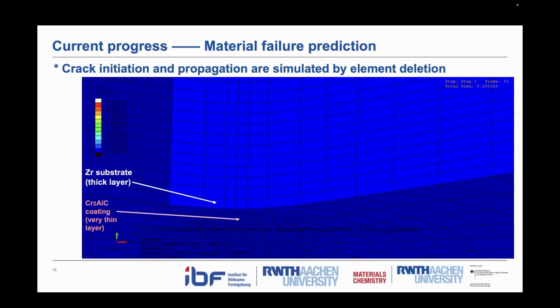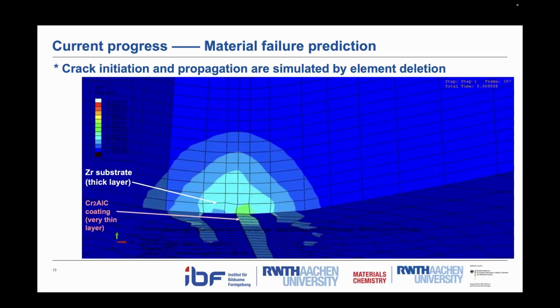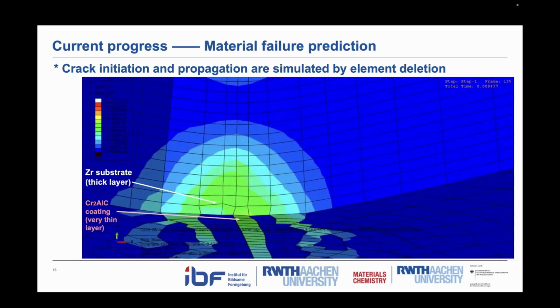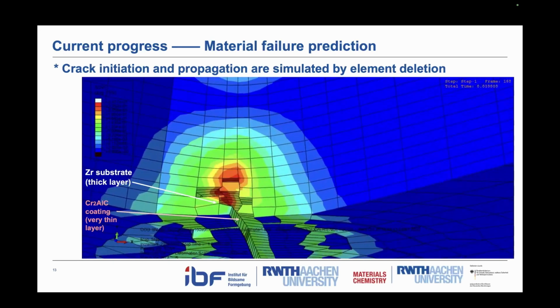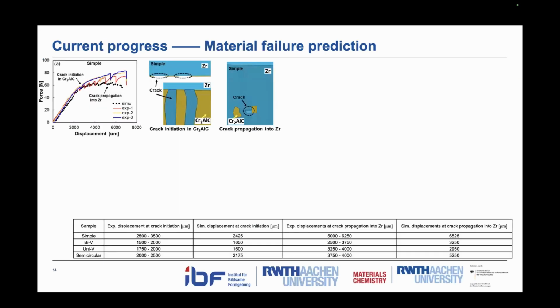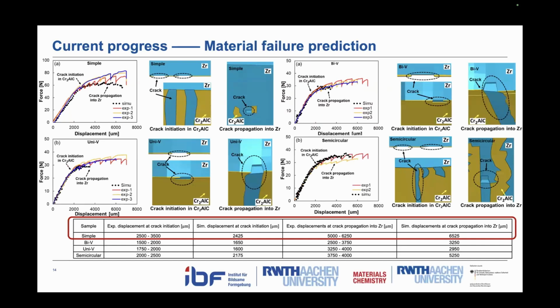So first of all, the cracks initiate in the coatings by element deletion, and then with further loading, the elements in the substrates were deleted, which means that the cracks propagate from the coating to the substrate. And if we compare the results statistically, then we can see that we managed to replicate the force and displacement curve, and also the crack initiation and propagation with very good accuracy. So this sample is an example for presentation, and for the others, it is the same.